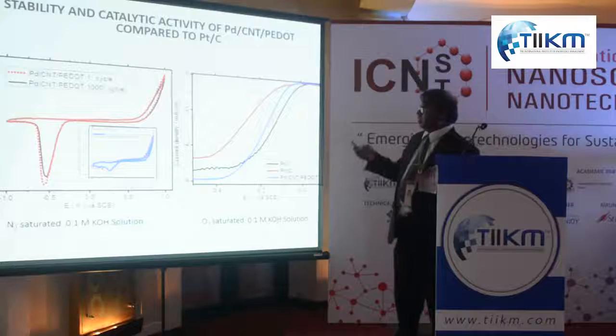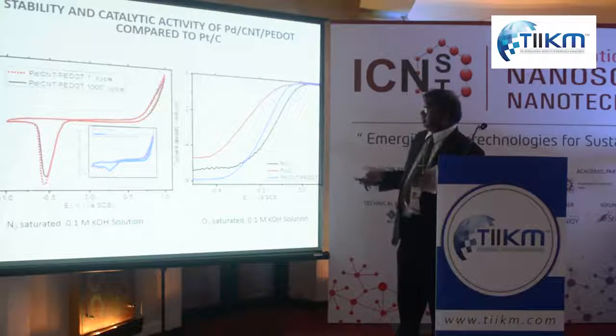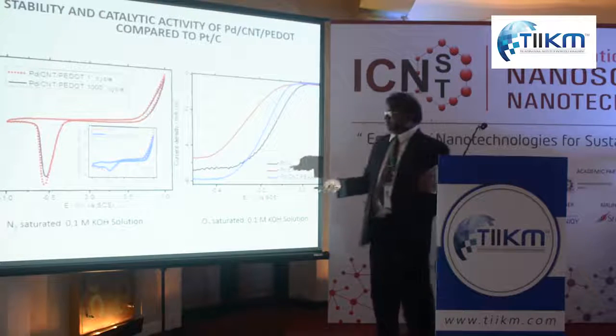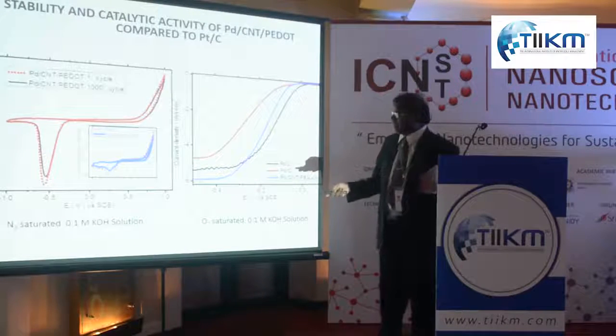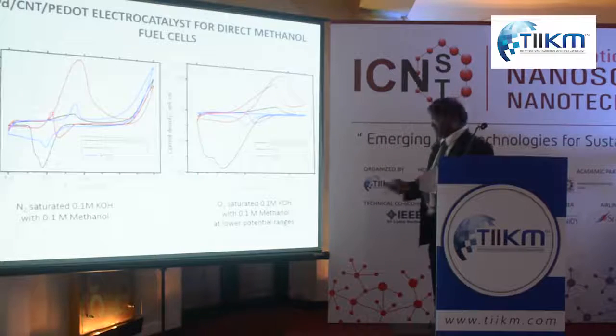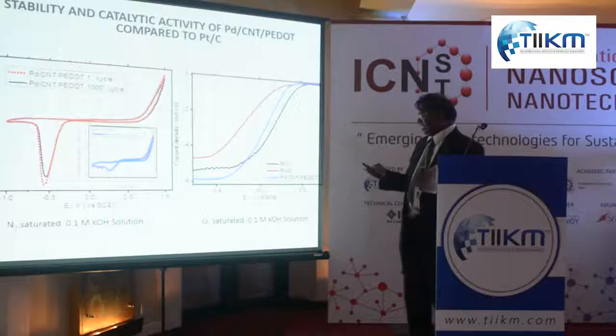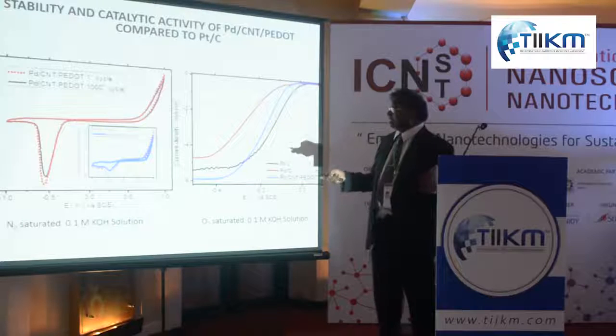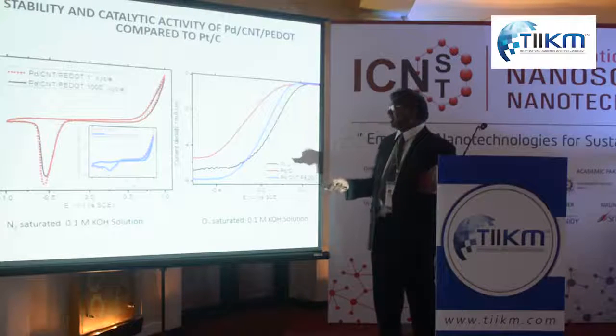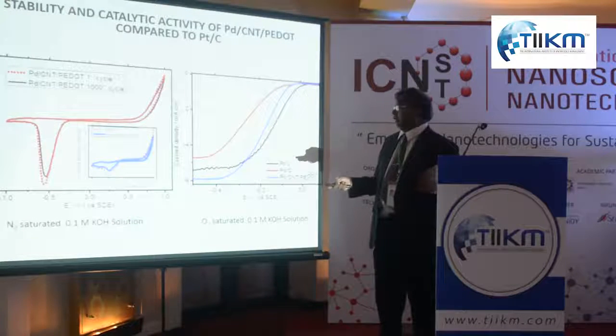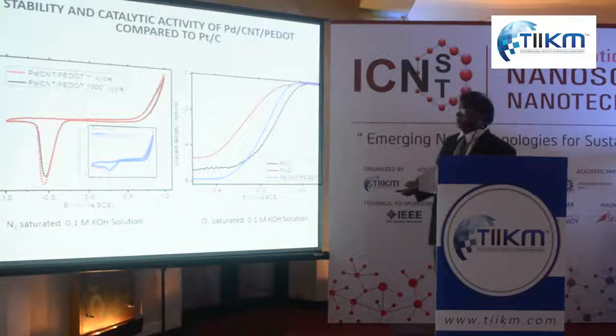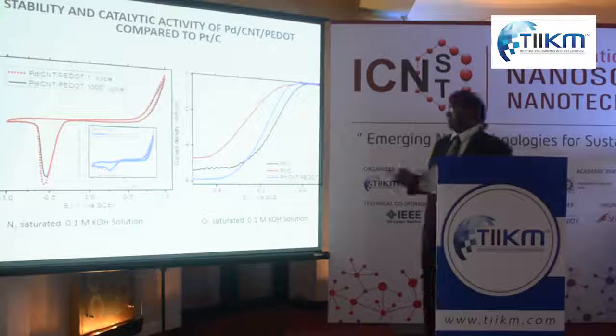And you see the first cycle and then 1000 cycle. First cycle is this red one, 1000 cycle is black one. Sorry about that. First cycle is there, 1000 cycle is there. So there's a very small change in its activity, you see, after 1000 cycles.